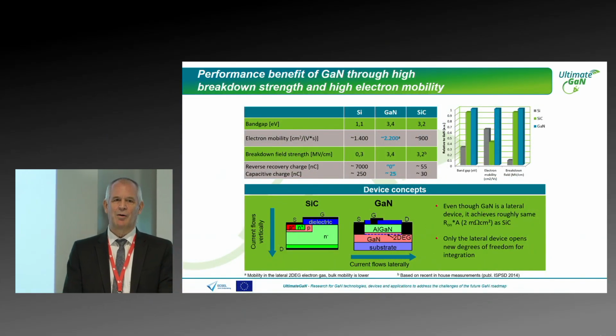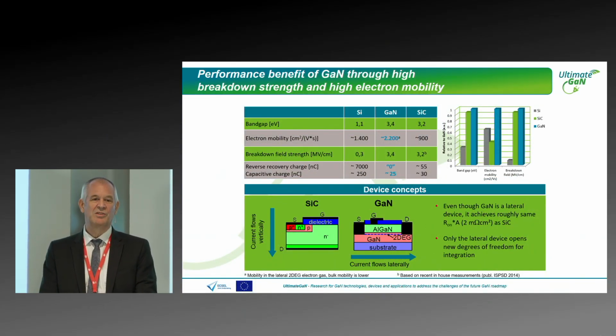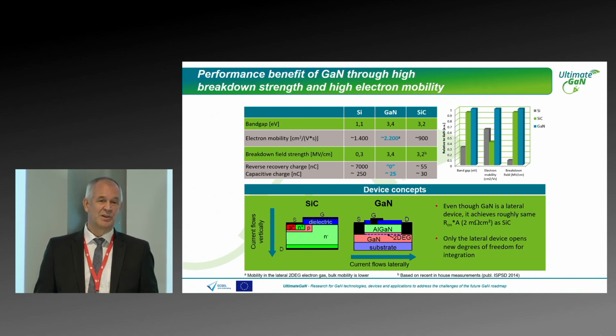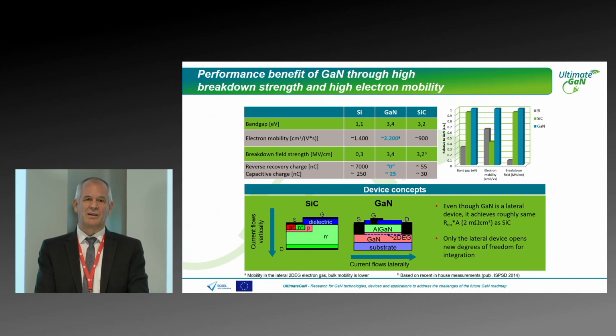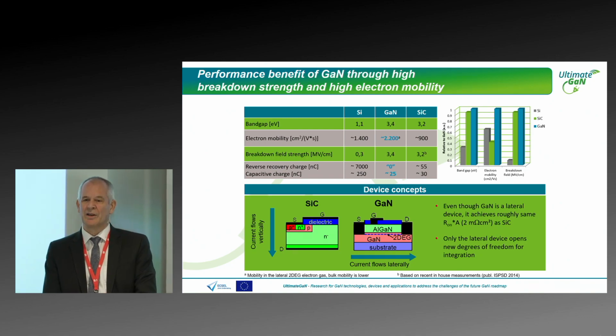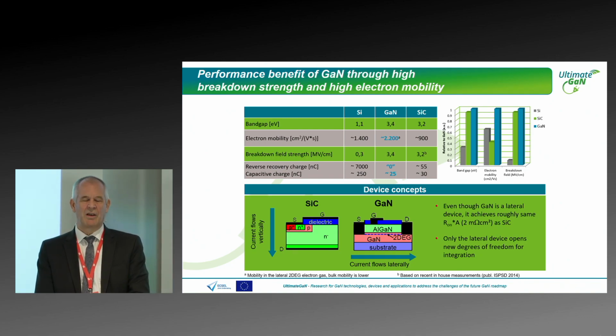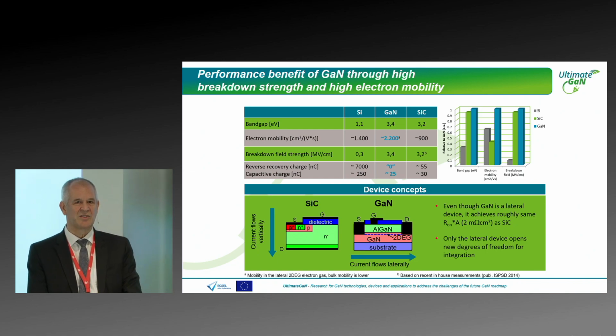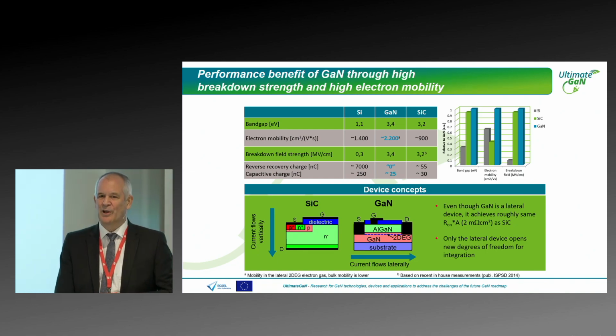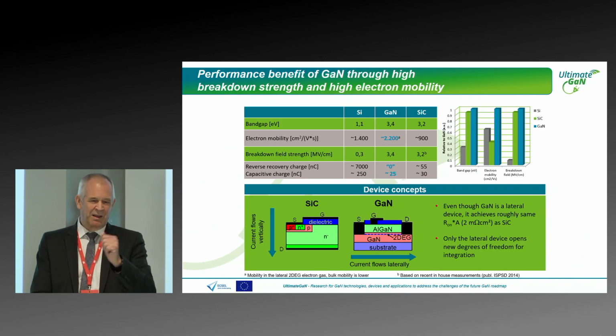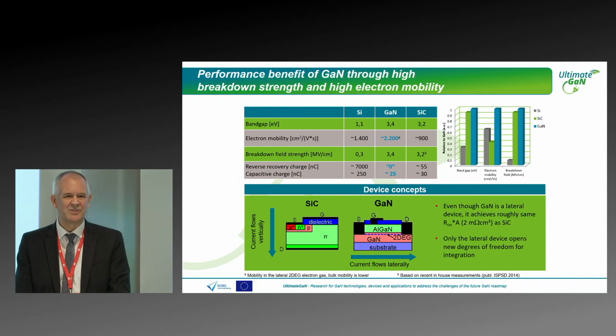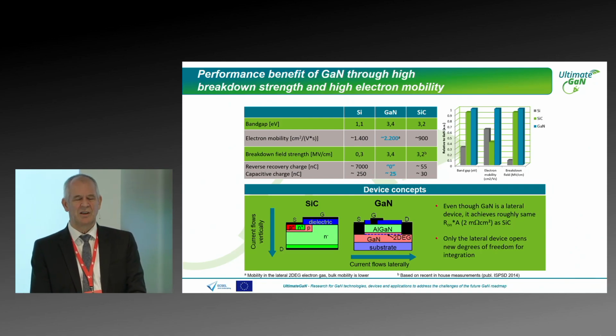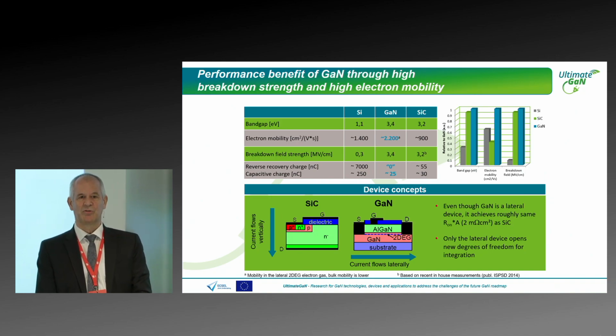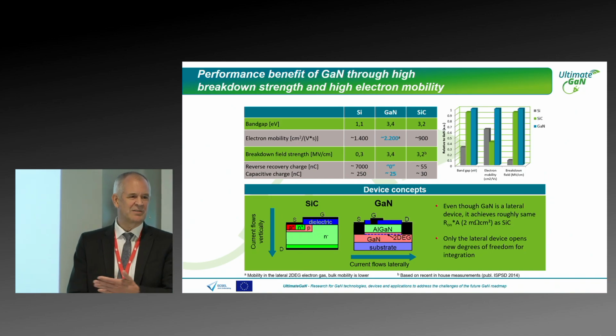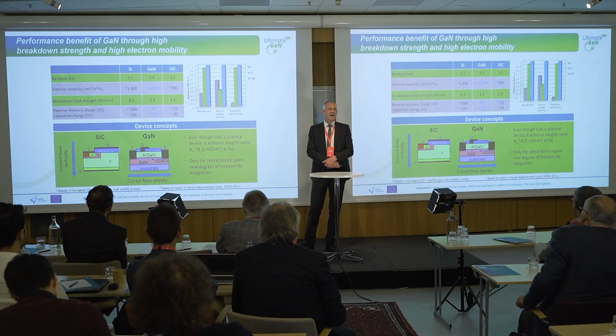Because in silicon carbide, it's not the mobility in the volume, it's the mobility at the channel. And this is still very poor. And it's gallium nitride with a two-dimensional electron gas. This is about 20 times higher. So Herbert's gut feeling: you cannot betray physics. So for the lower voltages, I see GaN in a very favorable position. And for the higher voltages, as everybody said, yes, it's hard to compete with silicon carbide.